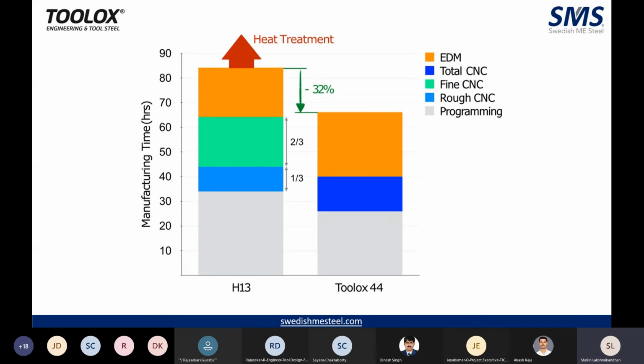So this gives you an idea of how much time Toolox 44, which is pre-hardened at 45 HRC, takes when compared to a regular annealed H13 material, or D2, or whatever material you want. So we have tested based on H13, and what does it say? Since it's a 45 HRC material, there is no need of two times of programming. At annealed as well as after heat treatment, you need to do another set of programming. Here, with Toolox 44, it's only one set of programming.